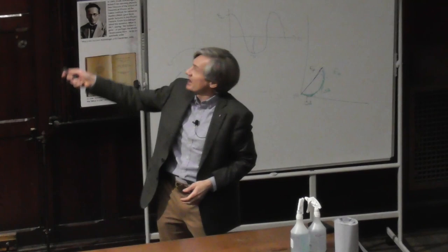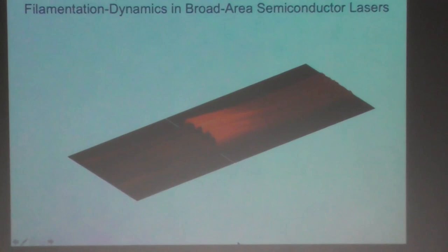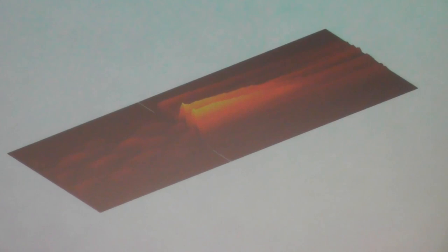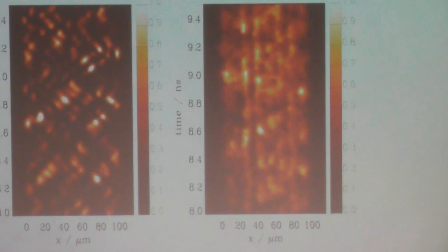However, if that laser now was a little bit bigger, this is now the cavity, what comes out at the sides is very different. You could see that suddenly along that lateral direction, this transverse direction, filaments have formed. These streaky things that came about were not stable, they were shifting, and as a result, the light emitted from that laser was anything but stable, kept on being unstable. So the laser property actually was completely lost.